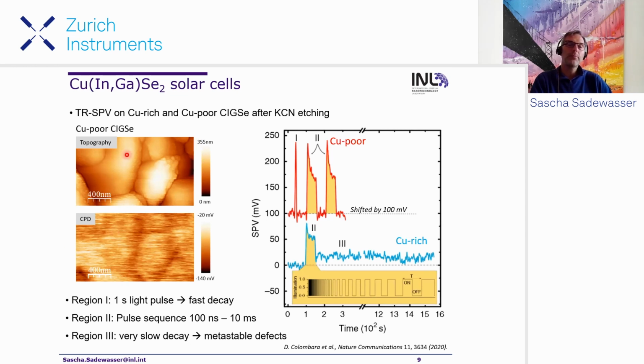Note that these samples are fairly rough. So this is far away from nice, flat, ideal surfaces with atomic resolution. Normally our images are a few microns in size, and we have surface height differences of a few hundred nanometers. So just the topography scan often is somewhat of a challenge. Then when we put a constant illumination on it with a red light, which is above the band gap, we see that the surface photovoltage increases here. And then when we switch it off, it immediately decreases.